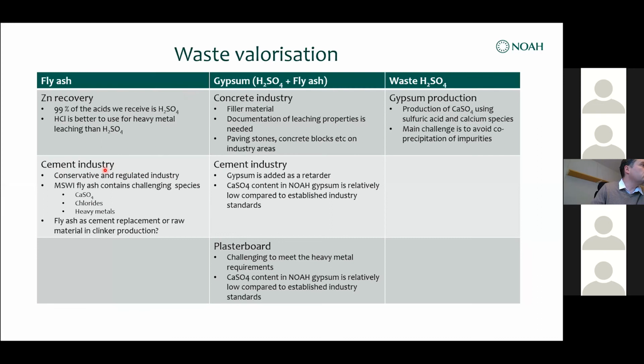The cement industry, we have also been looking into that and have a great dialogue with them. This is maybe my view, but it is a fairly conservative and regulated industry, which is completely understandable because they deliver cement for buildings that should stand for 100 years, so you don't gamble with what you put into the cement. The feedback we get is that the fly ash has way too high concentrations of calcium sulfate, chlorides, and heavy metals. You can remove the chlorides, but you still have the heavy metals and the sulfate. The next question we should ask ourselves is whether our fly ash from the municipal solid waste industry should be used as cement replacement or raw material in clinker production, because I strongly believe you cannot compare our fly ash with fly ash from coal combustion. It's two different products.